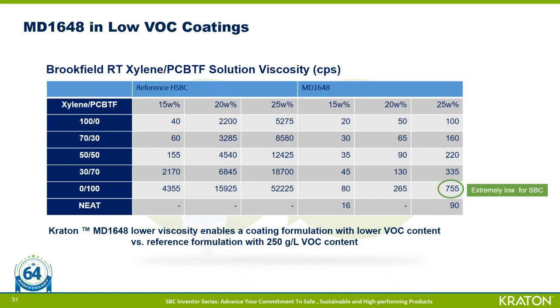So for example, the number circled in green on the far lower right of the table is the solution viscosity of MD1648 at a concentration of 25 weight percent polymer in a solvent that consists of PCBTF and contains no other solvent, in this case 0% xylene. So here the viscosity is noted as only 755 centipoise, which is extremely low when you're thinking about the 25% polymer content in a VOC exempt solvent, which typically have higher viscosities than VOC containing solvents.